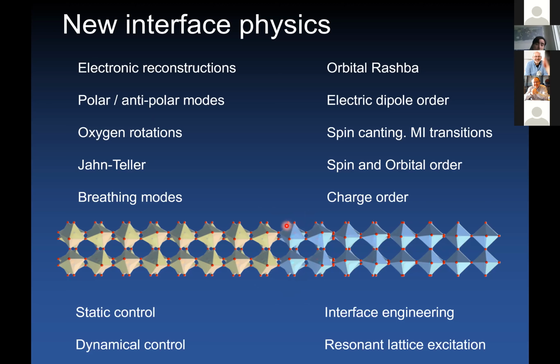So you have an interplay between electronic reconstruction that brings in new orbital physics and a structural reconstruction. So you can have stabilization of polar or antipolar modes, which involve electric dipole order, which may strongly influence your electron system at these interfaces. You can change oxygen rotations, which may influence spin coupling and therefore be active on the magnetic phase transitions and metal to insulator phase transitions by renormalizing the hopping. You may be touching upon Jahn-Teller distortions, which will influence spin and orbital order, or breathing modes, such as in the nickelates, where you have a checkerboard pattern of small and large oxygen octahedra, so you're touching upon the charge order of this system.